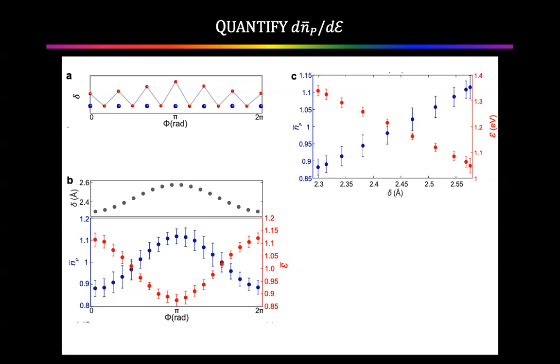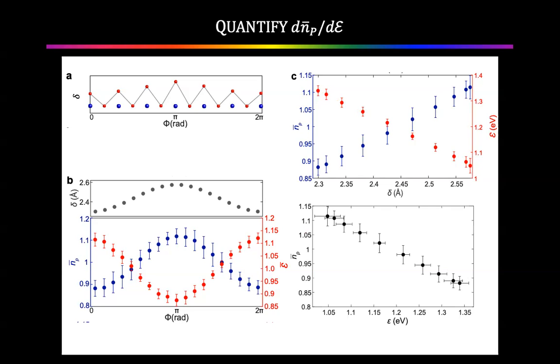Now, forget the apical distance. That was a motivational tool. Here, it's just a common variable. What we really want to know is what happens to the electron pair density as a function of the charge transfer energy. So we can just remove the common variable, which is the phase, and plot electron pair density versus charge transfer energy while the apical atom moves 0.3 angstroms in this context. This is the depth. It's averaged over large fields of view, so the statistical error is fairly small. Systematic error has to do a lot with assumptions that go into this project, so we can discuss those. But statistically, it works fine.